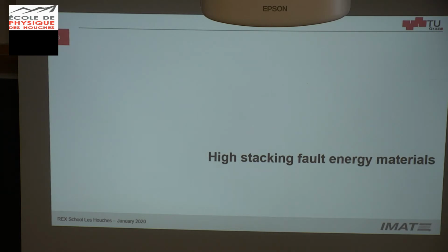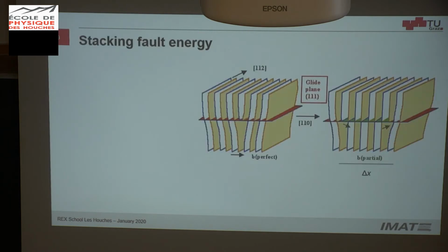And what they have in common is that they are high stacking fault energy materials. What is the meaning of this? The meaning of this is that if we have a perfect dislocation, this perfect dislocation can dissociate into two partial dislocations. And this configuration here does not allow dislocations to move. So it's very difficult for a dislocation to go through stacking faults, first of all. And secondly, you lose the dislocations that move, because they split into two partial dislocations that are not moving anymore.